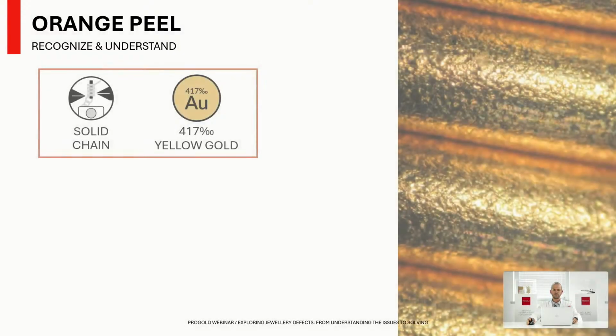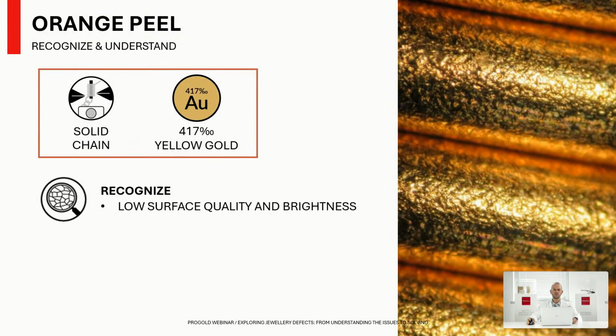The third defect that we will see is the orange peel. Orange peel is a defect that regards the plastic deformation process. What we are seeing is a solid chain produced in yellow gold 10K that shows this typical morphology that is called orange peel. It's like the surface of the orange fruit, and it affects the quality and the brightness of the mechanicals on the wire and the sheet after annealing and deformation.